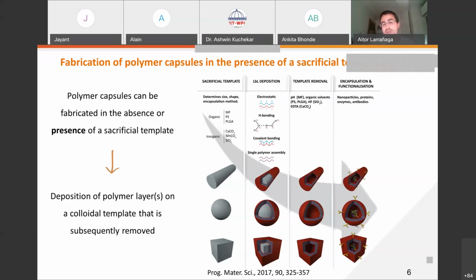So then, once we decide what kind of sacrificial template we want to use, we proceed with the layer-by-layer deposition of the polymeric layer or layers. And this usually happens by either electrostatic, hydrogen bonding, or covalent bonding interactions. So once we have deposited the polymer layer or layers on our sacrificial template, we proceed with the template removal. And this will be directly dependent on the kind of template we use, of course.